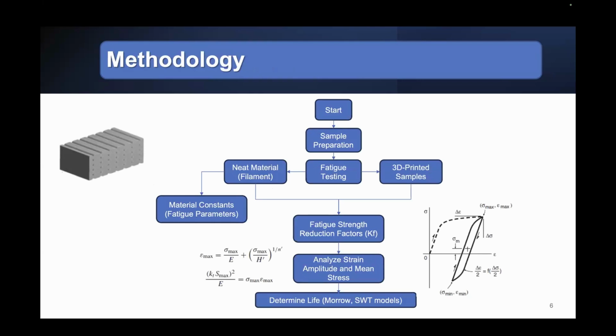The methodology. Here we can see that there are some discontinuities between the filaments of a FDM process sample. The idea of this study comes from this fact that these discontinuities between the filaments can act like a sharp notch, and this notch can reduce the fatigue life of the component substantially. So we start with sample preparation. Then we do some fatigue testing on neat material as filaments and 3D printed samples.